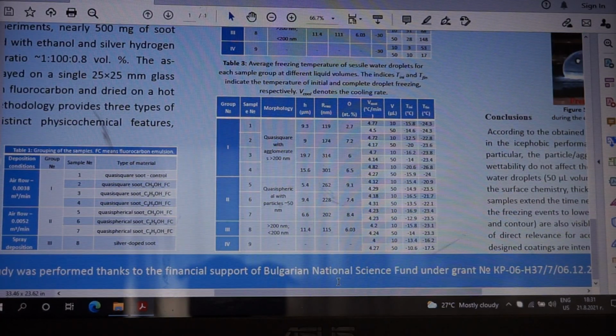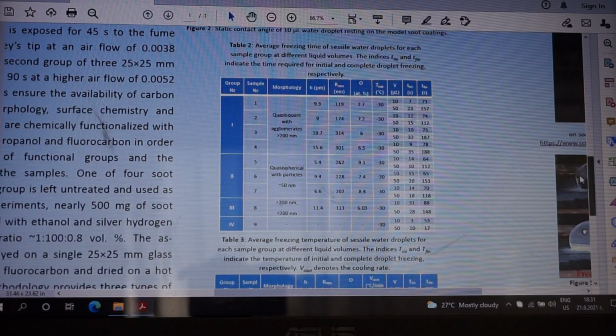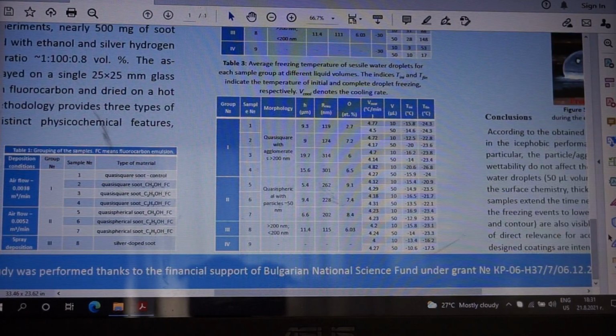So, the evaluation of 8 multifarious soot coatings under nearly 100 experimental cycles, the results of which are presented in tables 2 and 3, show that the soot particle aggregate size, surface roughness and degree of non-wettability do not affect the ice-phobic performance of the coating. The film's thickness, air fusion arrangement and surface chemistry are the main parameters governing the anti-icing efficiency of the soot. In particular, the chemical bonds of the soot tailor its interfacial thermal conductivity and control the freezing time delay and freezing temperature depression.